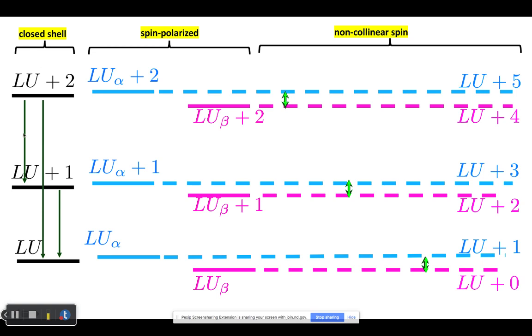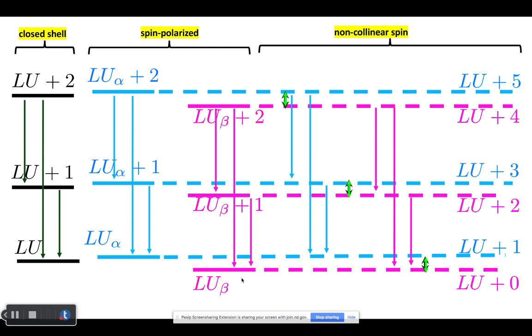So let's look at the left. If we didn't have any spin, closed shell, we have only 3 transitions, plus the opposite direction, right? So total 6. It is a 3 by 3 matrix, and the diagonal does not count when a particle stays at the same orbital. If you do have spin polarization, you have similar transitions going down, 1, 2, 3. For alpha, going down from 2 to 1, 1 to 0, and 2 to 0, right? So total 6 transitions. But if you are going to non-collinear spin, we will have the same transitions from the former alpha to former alpha, 3 transitions, blue color here, then pink, former beta to former beta, another 3 transitions. But it is not the whole story. Those were spin conserving transitions, when the spin projection doesn't change.